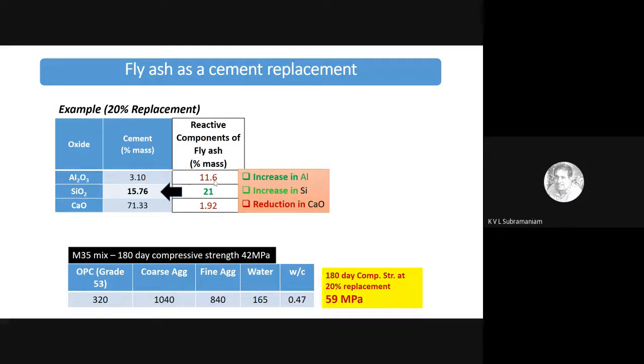And when I replace, let's say, 20% of the cement with fly ash, and I'm only showing the reactive components of fly ash, the fly ash that we used in this case gave 21% reactive silica. So it had 21% by its mass reactive silica. It had 11% alumina in reactive form and only 1.92% calcium. So if I replace cement with fly ash, I increase the alumina content, I increase the total silica content in the system, but there's a reduction in the calcium oxide content. So this is the trade-off.